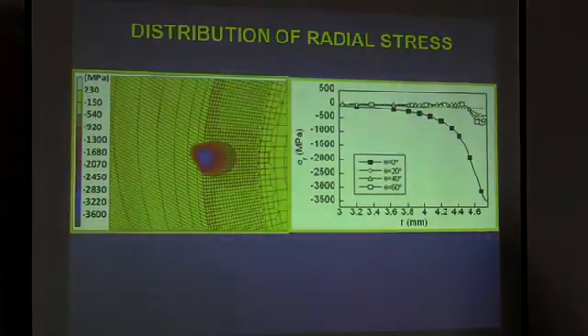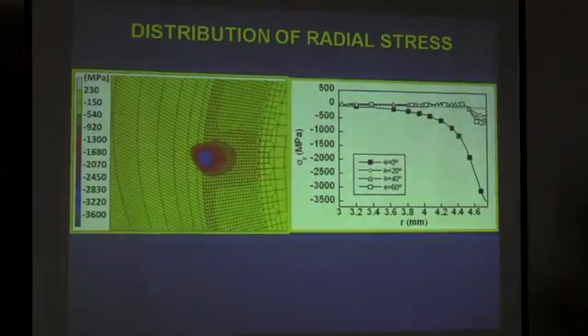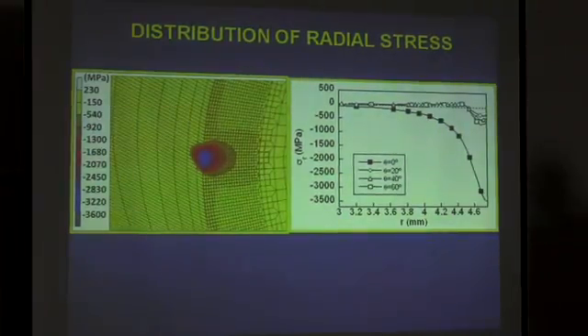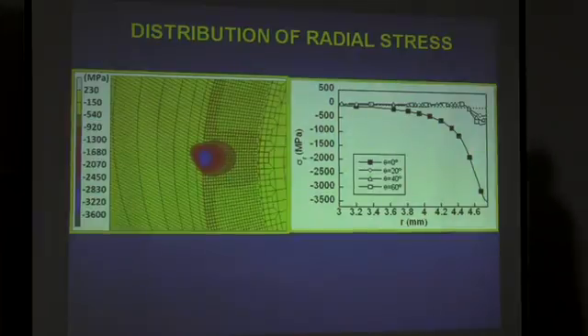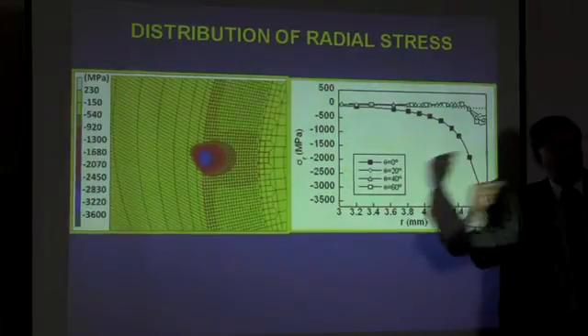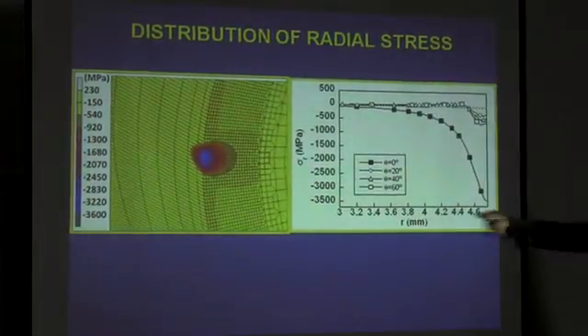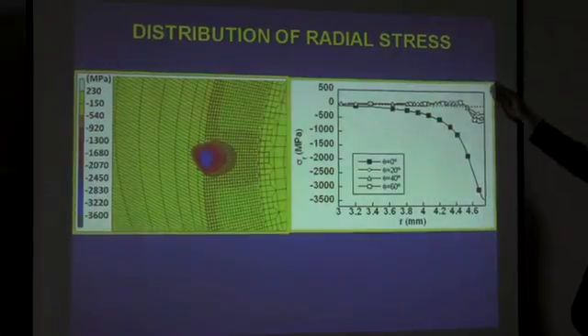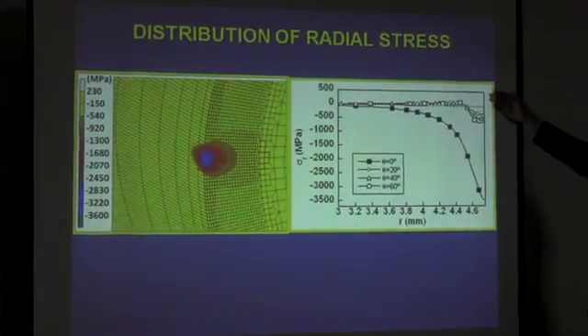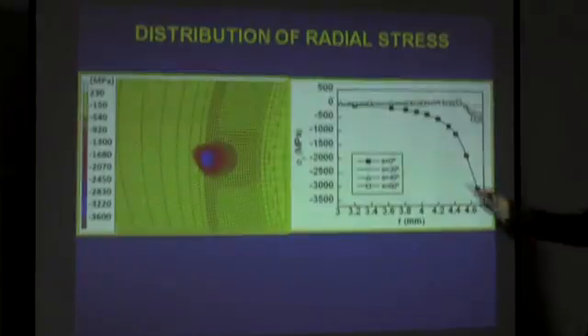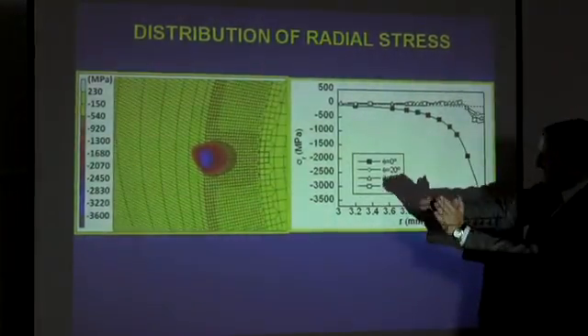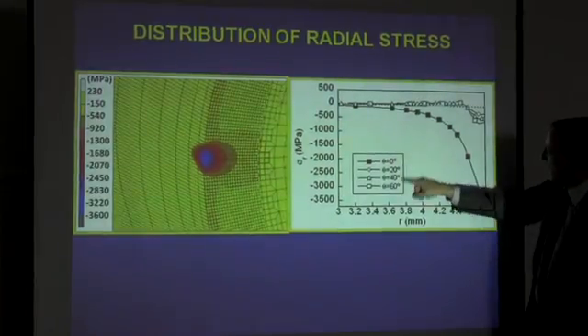Let's go to the mechanical analysis. The distribution, we have analyzed in the 3 terms. This is quite multiaxial, the 3 terms of the stress tensor. This is the radial stress. This is the contact between the ball and the rod. And here we have the radial distribution. This is the contact with a concentration, and we have negative radial stresses. 0 degrees is just the plane of the contact, and different angles for the contact plane.